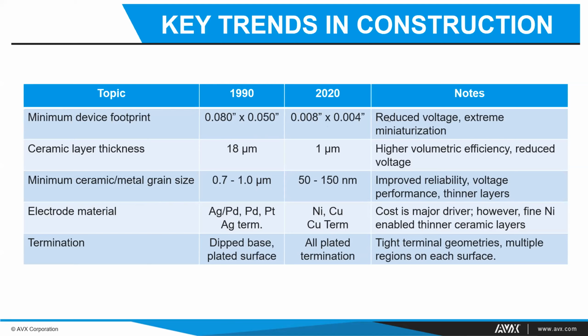Now obviously that does imply some reduction in the voltage that would be applied to these devices, but you can see the sense of extreme miniaturization that is available from multi-layer ceramic devices these days, and I think that's pretty impressive. Ceramic layers are concomitantly smaller. Back in the day, you might say that the 18 microns was one of the thinner fired layer that you'd see, but now 1 micron is fairly common, and people are reaching below that thickness. And this has given us higher volumetric efficiency and reduced voltages.